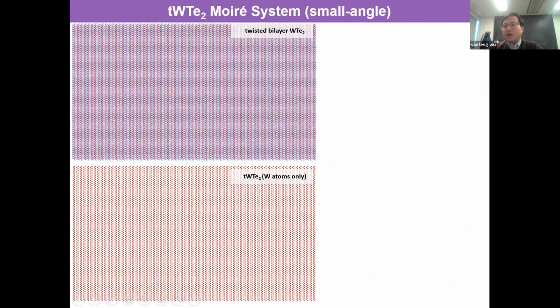So monolayer tungsten ditelluride is difficult to study in a wide range of doping, especially near charge neutrality or hole sites, because it's very insulating. And the quantitative measurements of insulating states in resistance, for example, are quite challenging. So what we try to do here is to put two layers together so that the sample becomes less insulating.